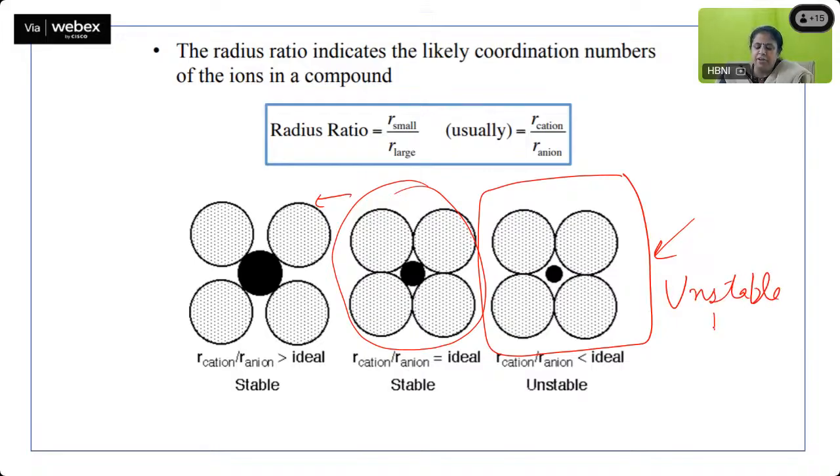And when you reach this situation, the coordination number for this particular pair of cation and anion would be lesser than 4. Similarly, in the other direction, as the cation keeps on increasing for the same anion, ultimately a situation would be reached when it would tend to adopt the higher coordination number. That is what sets the guideline on the boundary line for a pair of cation and anion regarding the coordination number they can adopt.